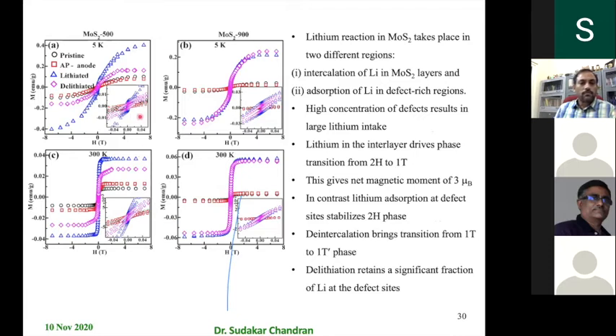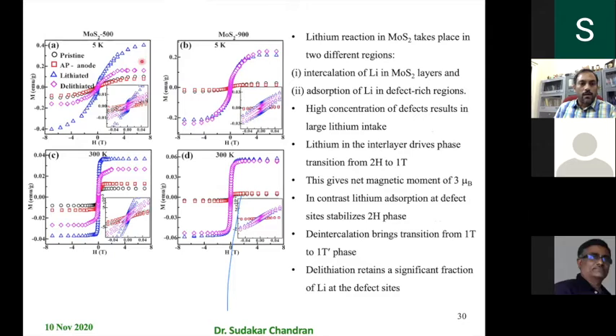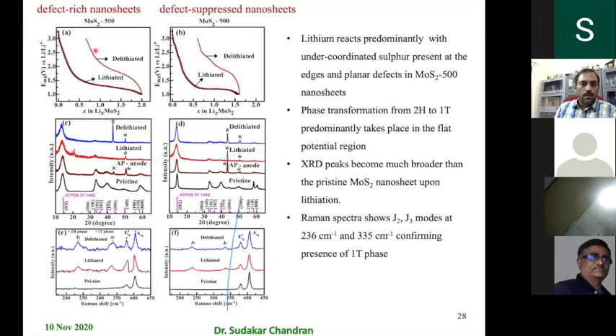In any case, if you look at the magnetic properties, the pristine one is the black here, very small, right? And then the moment you do the lithiation, the blue triangle here, it jumps from here to this much. So there is a big jump in the ferromagnetic nature that you can also see when the measurements are done at room temperature. When you reversibly extract the lithium, then the magnetization comes down. So for the reversible extraction, as you can see here, initially we could put 2 lithium in, but when we reversibly take it out, we could get approximately 1 lithium only in both the cases.